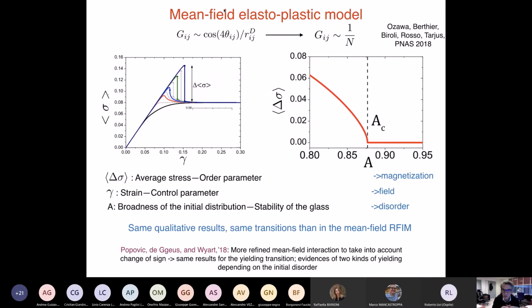Now, the interesting news is that you can try to do a more refined mean field interaction in which you still have something which is long range, but which can change sign. This is what has been done by the group of Matthieu Wyart. And they still found the same property of the yielding transition, which again is the same as the mean field random field Ising model.